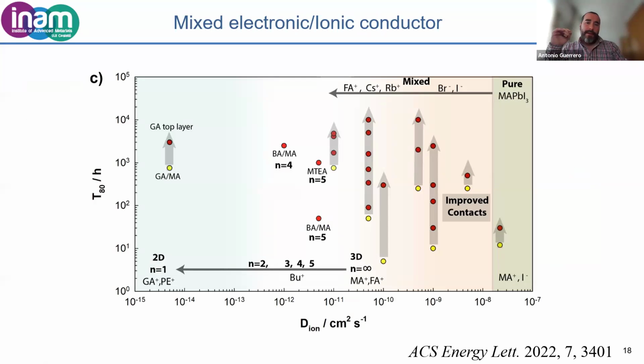So this ion migration, how the materials are migrating, is closely related to the stability of the devices. In this plot, we show how the ion migration, how fast the ions would reach the contacts, is connected to the T80. The T80 is a parameter that details the time that it takes for the solar cell to decrease the initial efficiency by 20%. And this is a good descriptor to describe the degradation of the device. So the graph is complex, so I will take you through it a little bit.